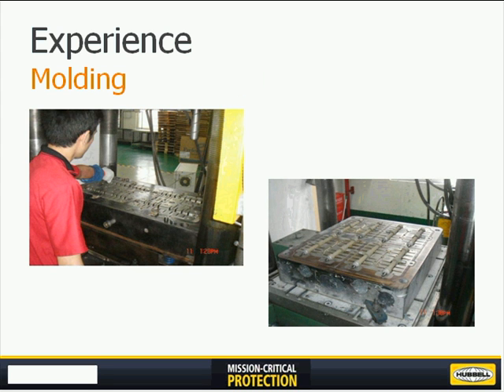Here you will see a picture of the molds used for the polymer cutout. Prior to going into molding, one of the other critical components, which we mentioned earlier, is the interface. So prior to molding, all of the rod assemblies, which is what the pultruded rod and the end fittings are known as when they're connected together, are coated with an adhesive to allow the polymer to stick. Throughout the years, we've made significant improvements in the application of the adhesive as well as the adhesive itself. Being different materials, the core rod and the stainless steel fittings, it's difficult to maintain your rubber interface on both materials.